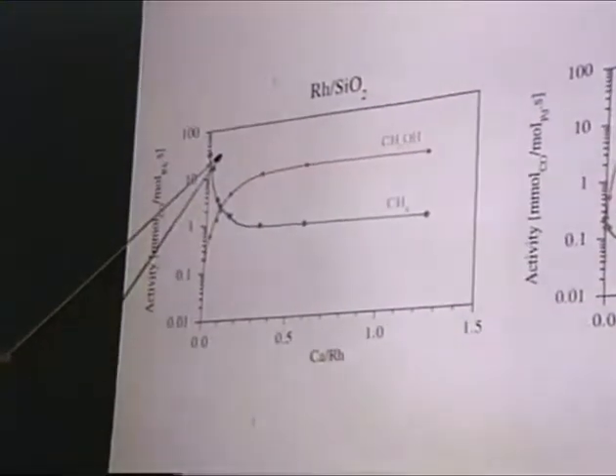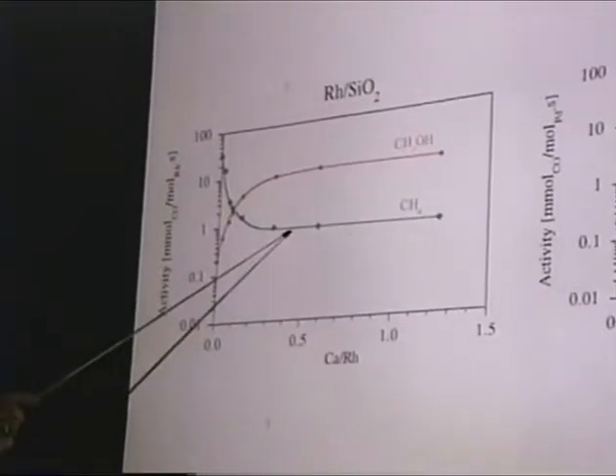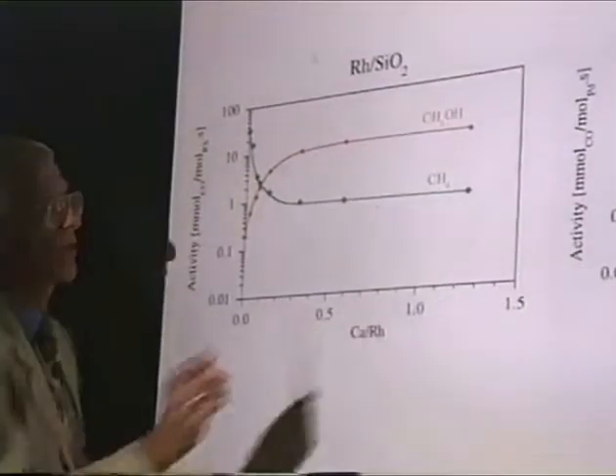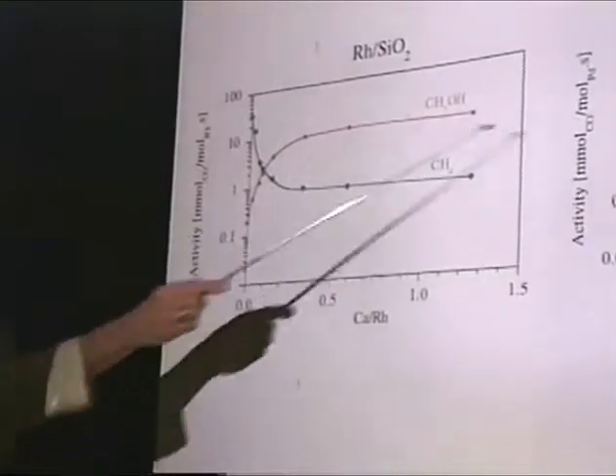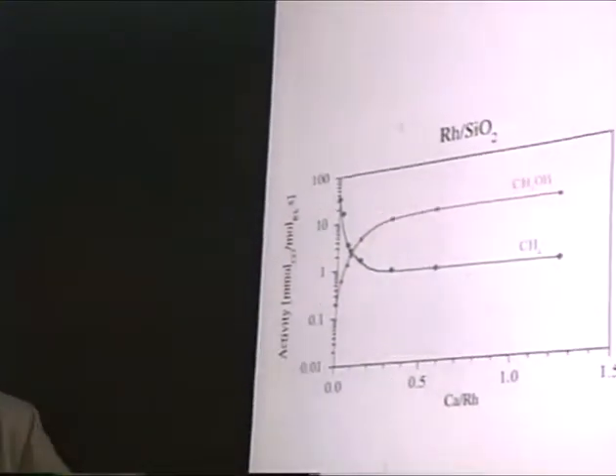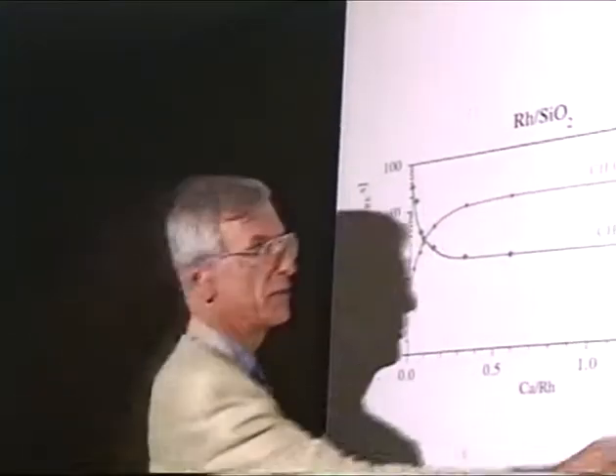The rhodium starts with a much higher level of methane, of course, and you can also suppress it, but not so deeply as the palladium. And the methanol goes up to, as you see here, almost the same level. This catalyst was a little bit better dispersed than that one, but the difference was not much. So this catalyst only has 90% selectivity. Also note that you need somewhat more calcium here to really be in the constant area than for the palladium.